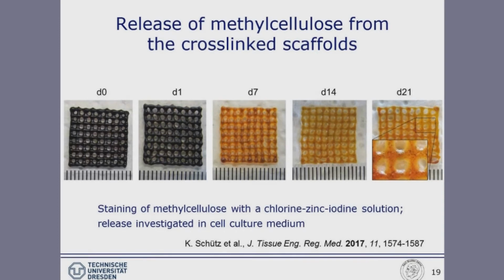The nice thing about using methylcellulose to blend the alginate is that the methylcellulose, of course, is not cross-linked by calcium ions, in contrast to the alginate. And therefore, the methylcellulose is more or less quantitatively dissolved already in the first week of cell culture. So here we just have stained the methylcellulose with a conventional cellulose staining, chlor-zinc-iodine solution, leading to this dark violet color. And you can see that between day 1 and day 7 storage in cell culture medium, most of the methylcellulose just has been washed out.